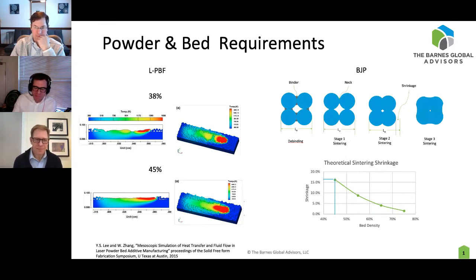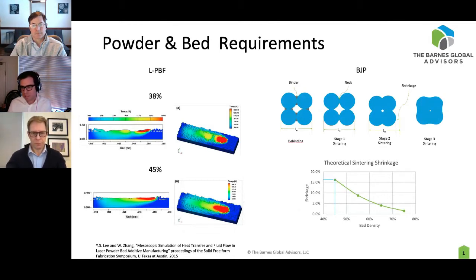Well, I think it's really going to come down to understanding the influence of the number of factors that go into the binder jet space. So with respect to the feedstock, how it's being distributed into the bed, which then interacts with the distribution of binder, which then, based off of how the powder particles are interacting amongst themselves, determines how good of infiltration you have by the binder. That can drive any kind of interlayer connectivity issues between individual voxels on a print, so that speaks to the interlayer porosity versus interparticle porosity. So it really depends on how well tuned and how well stress tested that process is to address some of the shortcomings, where we maybe can have a bridge in terms of understanding from powder bed fusion, to understand where we have just low energy defects versus high energy defects.